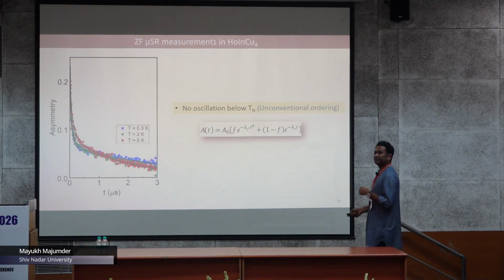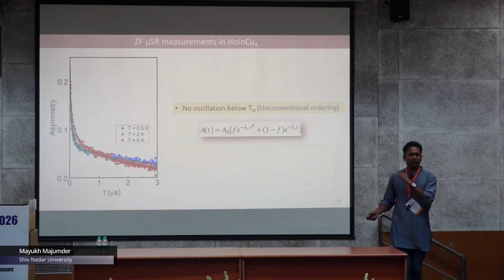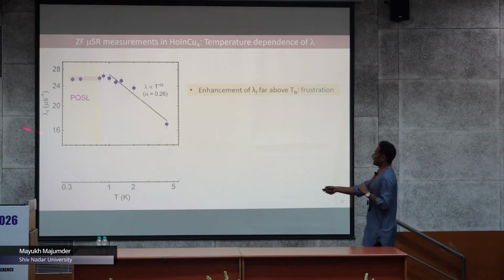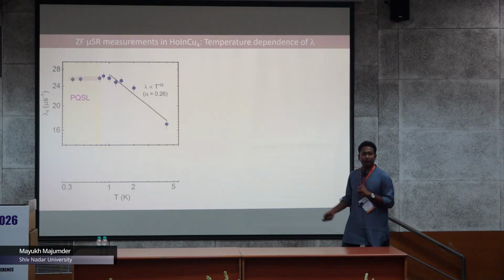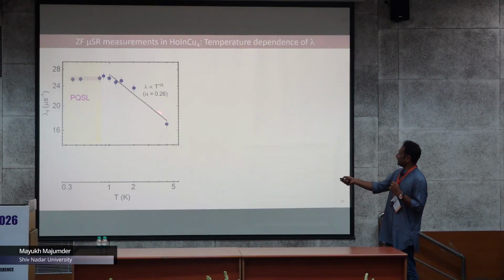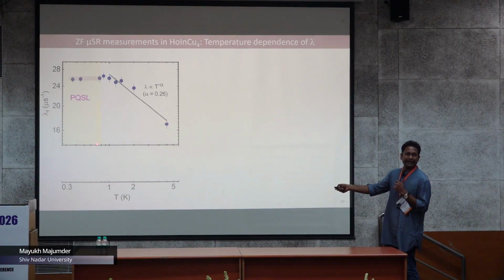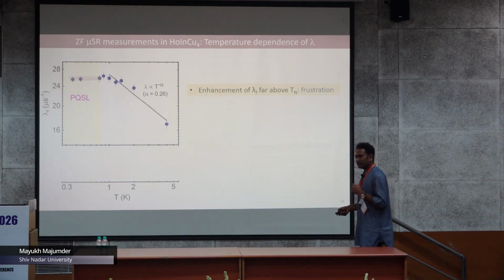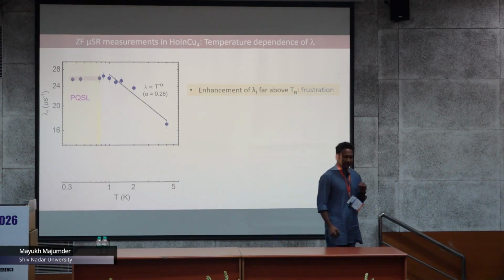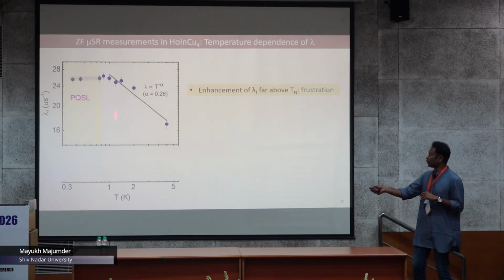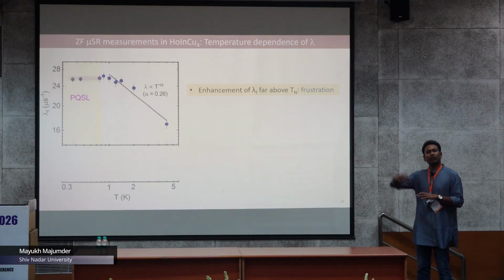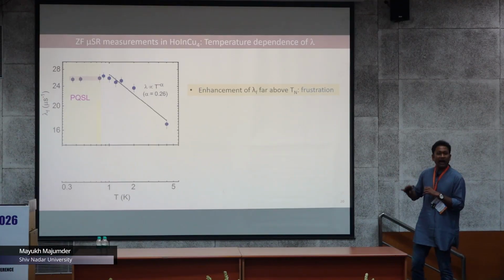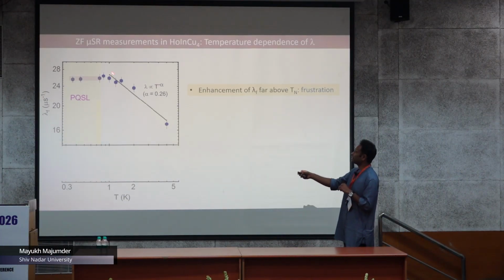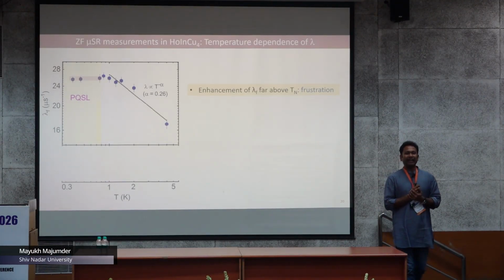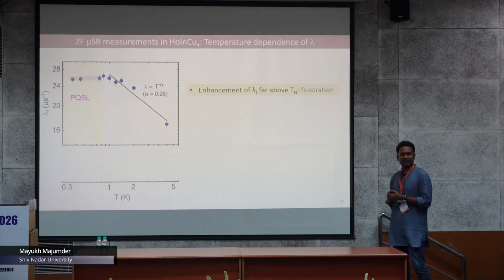So now let us see what is the temperature evolution of these 2 relaxation rates. First, let us see what lambda f is doing as a function of temperature. You can see there is an enhancement of this lambda f far above Tn. Okay, so that directly gives you the information that you definitely have some strong frustration, because in the case of frustration, you have short range correlations that start developing far above the ordering temperature. Unlike for an unfrustrated system, where you would be expecting the divergence or the enhancement of the lambda with reducing temperature just above the phase transition temperature.